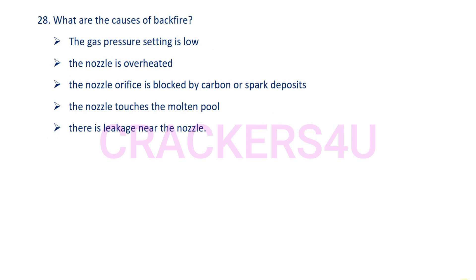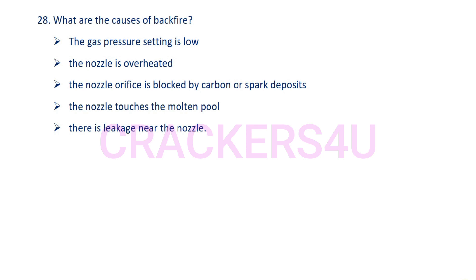Next question: What are the causes of backfire? Answer: The gas pressure setting is low; the nozzle is overheated; the nozzle orifice is blocked by carbon or spark deposits; the nozzle touches the molten pool; there is leakage near the nozzle.